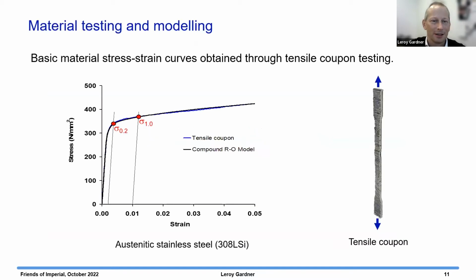Material testing. The first thing we wanted to know was what are the underlying mechanical characteristics of this material. You normally obtain these by doing what are called coupon tests. You can see one on the screen. We put the material in tension, we get the load and extension, and we convert that into a stress strain curve. And this characterizes the material response.